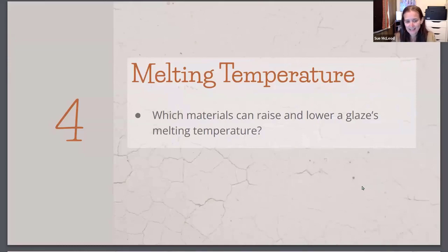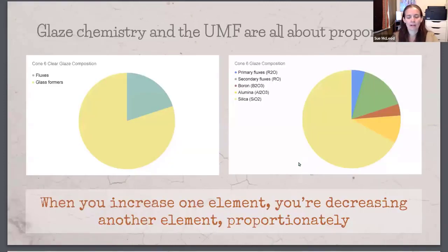Number 4, melting temperature. Which materials can raise and lower a glaze's melting temperature? So I talked earlier about glass formers and fluxes. Silica and alumina are the glass formers. I didn't really talk about alumina being a glass former. Alumina melts at an even higher temperature than silica. So alumina melts at cone 42, silica melts at cone 32.